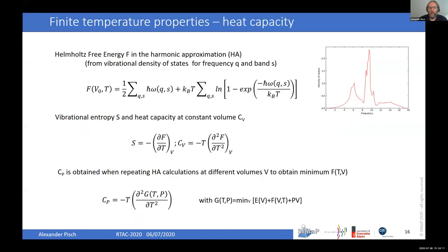But when we go to higher temperature properties, we need a lattice theory. There we compute the phonon spectrum, as you can see on the right for CaO. From this phonon spectrum and the energies of the phonons, the lattice vibrations, we can calculate the Helmholtz free energy in the harmonic approximation as given by this formula. And from this Helmholtz free energy, using classical thermodynamics, I can then calculate the entropy and the heat capacity at constant volume.